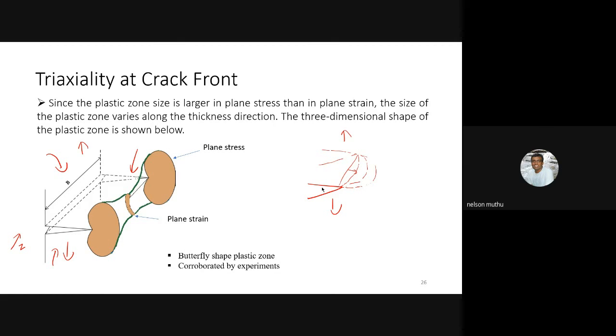So just to summarize, we have looked into Irwin's model, how we accommodated the plasticity, and also introduced the concept of effective crack to determine the effective SIF. But Dugdale and Barenblatt's perspective was slightly different. They assumed a strip yield model where at either end of the crack it was subjected to closure stresses, specifically sigma y as the yield stress, because it is an elastic, perfectly plastic material. They tried to calculate the net SIF and made it 0, because real materials cannot withstand infinite stresses. That was the basis for the Dugdale model.